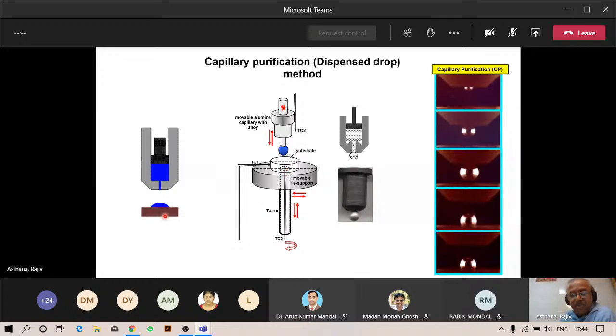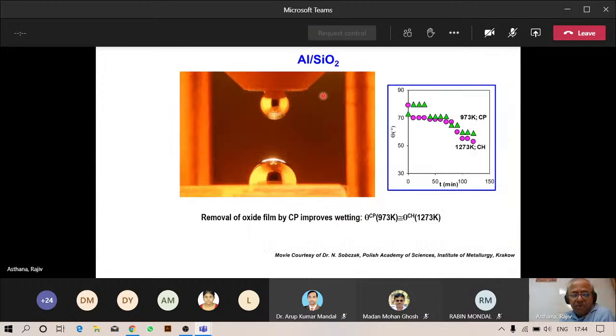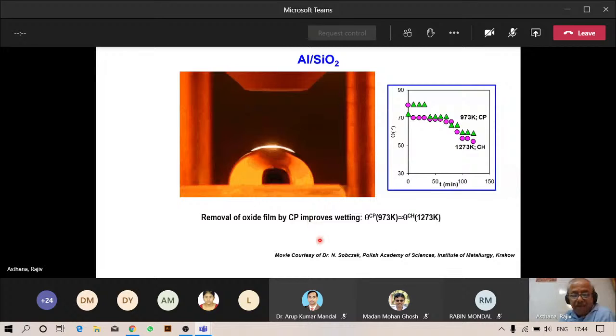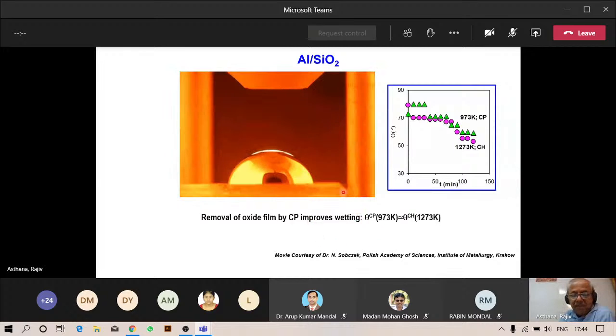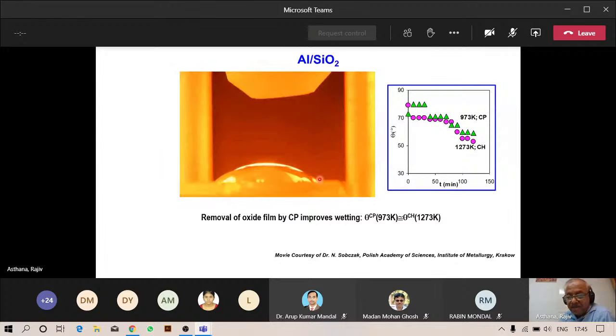So this was one approach we used using Dr. Sobczak's setup. And here you're looking at that example of squeezing aluminum droplet on a silica substrate. So what is happening here is that because of squeezing action, you are able to erode or remove the oxide skin on the surface of the droplet. And the droplet can spread out and give you good wetting in a braze or other type of systems. If you did this kind of an experiment using contact heating, you will get poor wetting.